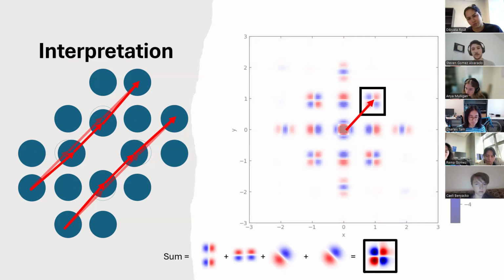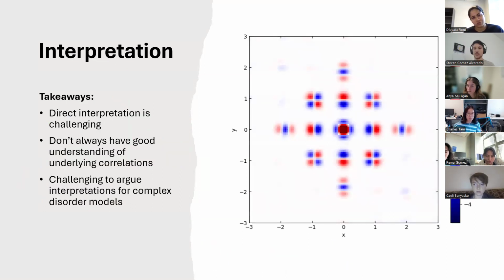It's very tempting to just eyeball the PDF, right? And just say, all right, I know exactly what's happening here. Atoms are moving away from the vacancy, right? Because this is a positive shift. It seems like atoms in a diagonal direction tend to move in this diagonal direction because there's increased intensity here. There's some displacement correlation over here. Like you can stare at this and try to come up with some story, but unless you have a model in your head of what's going on, you can easily mislead yourself into telling yourself the wrong story.